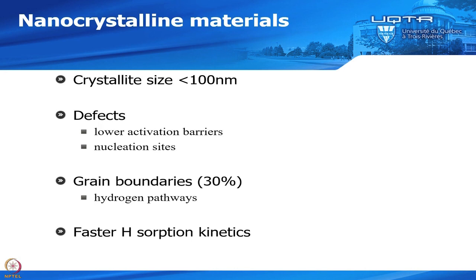In a nanocrystalline material, you have a lot of defects. These defects could act as activation nucleation sites, so they will lower the activation barrier. If you have more nucleation sites, your kinetics will be faster. And also, depending on the size of your nanocrystallite, the grain boundaries could make up to 30% of your material. And these grain boundaries could serve as a hydrogen pathway. So hydrogen could go through these grain boundaries to reach your nanocrystalline material. And all of this will make the kinetics much faster in a nanocrystalline material compared to a polycrystalline material.